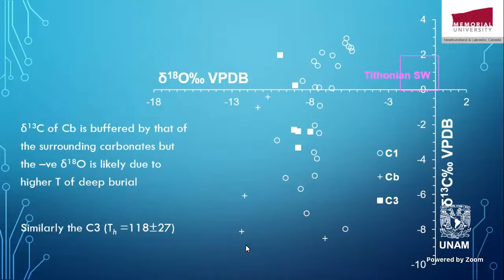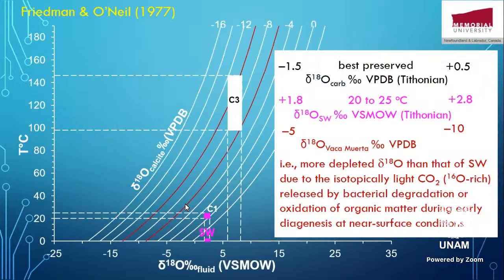And the C3 is very distinctive, as I said from the beginning. It has very distinctive negative delta oxygen 18. It's because the homogenization temperature is the highest. Okay, well, as I said, we apply the same equation of Friedman and the same concept.